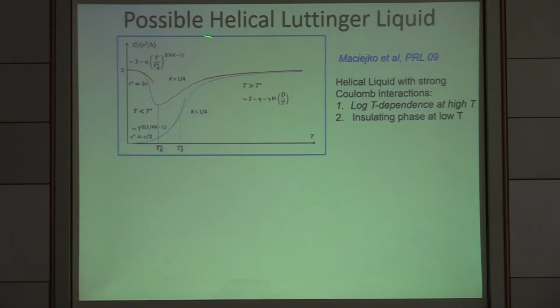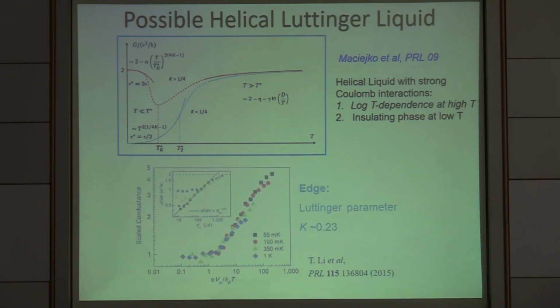Okay, so one can also look more deeply at whether this interaction is related to the helical Luttinger liquid proposed especially by this group. A helical liquid with strong Coulomb interaction can show logarithmic temperature dependence, and can also become insulating at very low temperature. So we did measure this edge state, and the behavior looks like a power law. One can get a power alpha of 0.37, and then you can calculate the Luttinger parameter, which is pretty small, 0.23. Okay, so that's getting into the strongly interacting region in this particular sample. This was published 2 years ago.